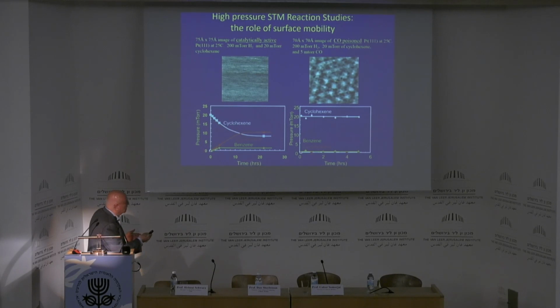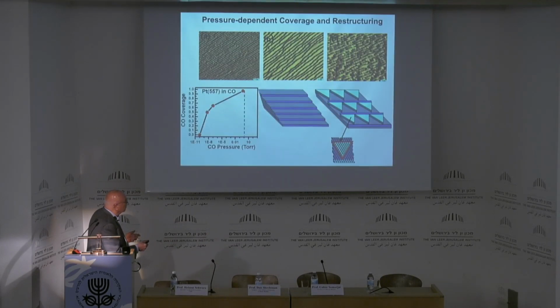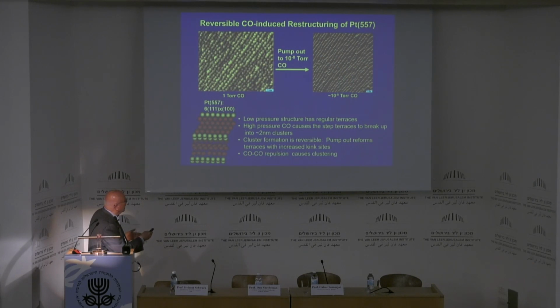However, if you poison the surface with carbon monoxide, you see the mobility stops, and there is no chemistry. As a result, the chemistry stopped here, and all you see is the poisoned surface. Not only that, but the surface itself is restructuring under the influence of carbon monoxide or another gas, and you can see the steps on the surface meandering and developing in a different structure. Once you remove the gas, the structure goes back to its step structure, and so the surface is in fact constantly restructuring, and this dynamics is at the heart of catalysis.